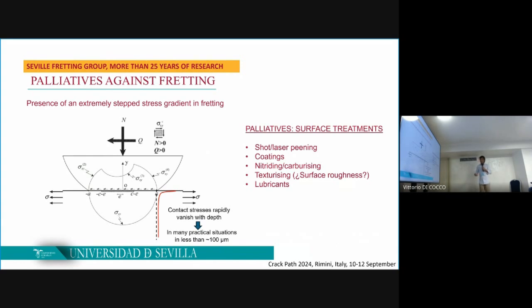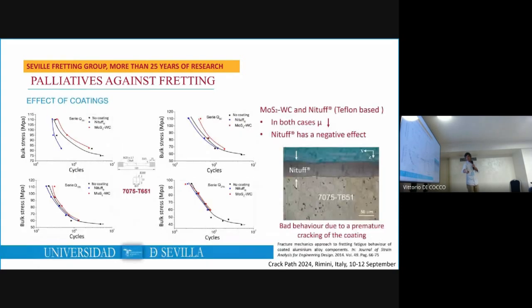For this reason, palliatives like shot peening, laser peening, coatings, nitriding, carburising, texturising, and also lubricants act as a very good palliative against fretting. It's also important to know that in many practical situations, this very steep stress gradient is reduced in less than 100 microns. For this reason, in the group, we have worked a lot with palliatives against fretting.